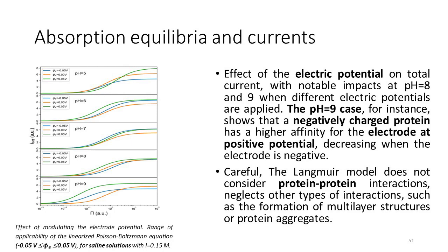Another thing that we need to mention about these absorption curves is that, as I mentioned during the methods, I use the Langmuir model. And in order to use the Langmuir model, you need to make a lot of assumptions. Basically you consider that the protein is going to behave ideally, so the proteins don't interact with one another, we don't create double layers, we don't create aggregates, etc., things that really happen during the absorption of the protein.